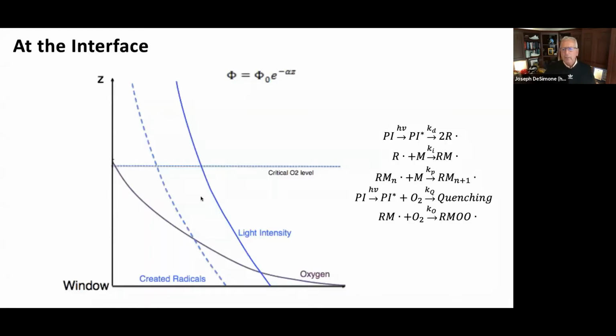And when you look at the details of what's happening, we have a z-axis going from the window up into the liquid resin. And then we have a general concentration axis here, where you're looking at the intensity of light as highest at the window as it exits the window. That light is generating radicals through a photoinitiator decomposition. And so the radical concentration is basically tracking with the light intensity as a function of distance from the window up into the liquid.